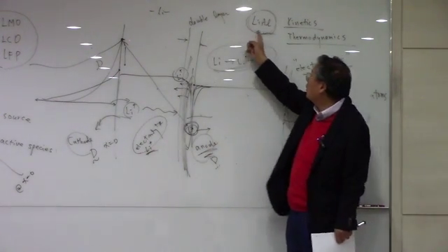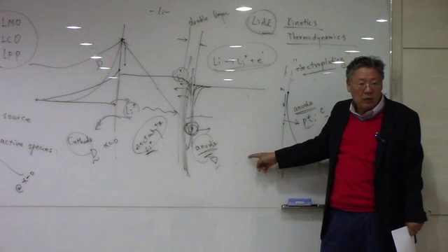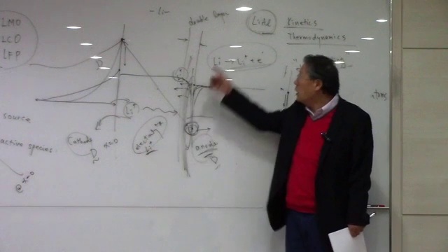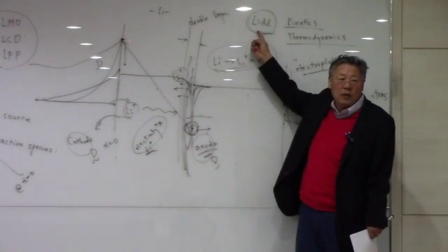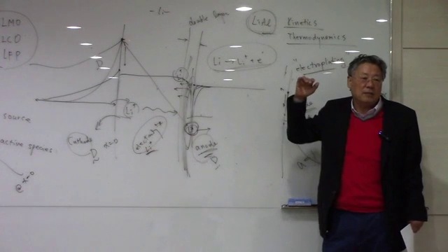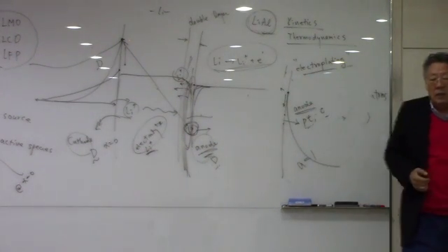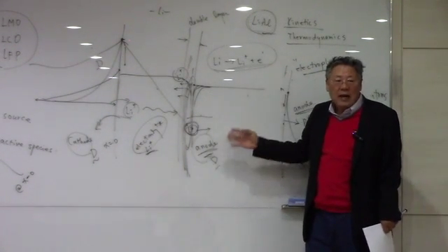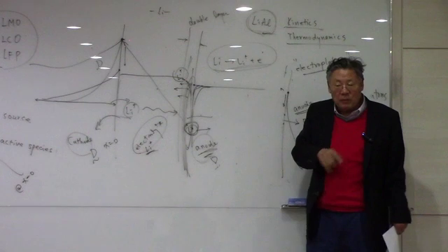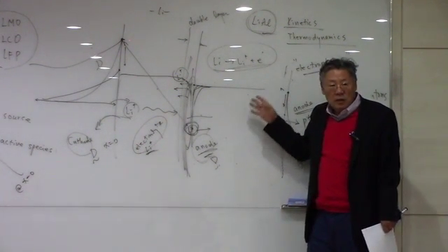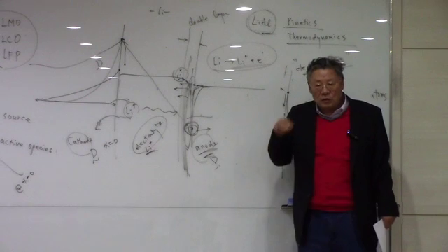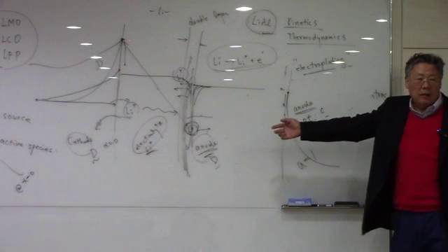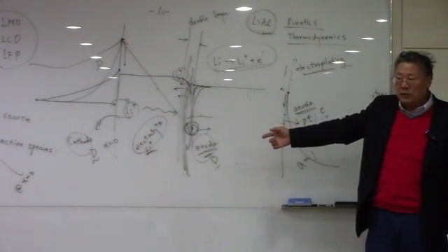But if you use lithium aluminum, for instance, as an anode, then you can fabricate the batteries in air, because the activity is not 1 in the lithium aluminum, so it is not that reactive with the oxygen. So people work on cathode and anode materials other than pure lithium in a lithium battery system just because they want to make the production cost low. And they have to pay in voltages.